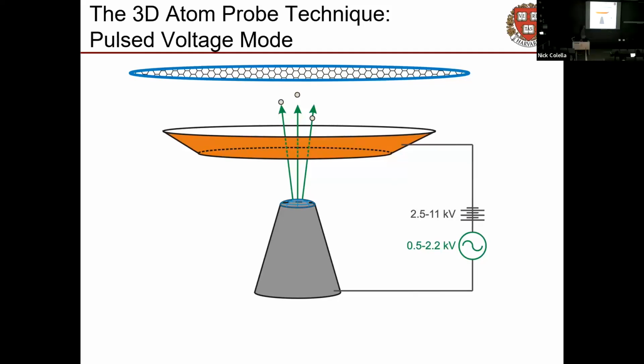So we put a few thousand volts on your pointy little tip with a counter electrode nearby, and we turn it up until your tip almost comes to pieces. We don't want it to just all explode at once, though, because remember, one of the important things about time of flight is we got to have that stopwatch, which means we got to tell it when to explode.